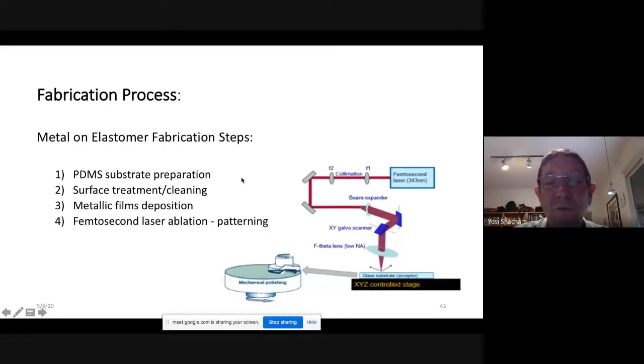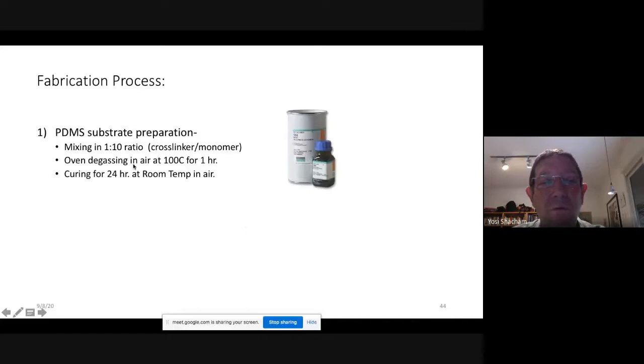First, one of the technologies which is very promising now, and many people are doing it, and we bought this system a few years ago. We are taking a laser, a femtosecond laser. We're using the 343 nanometer wavelength, which is ultraviolet. We're using pulses of approximately 270 femtoseconds. We have a Galvo scanner, so we can scan with the beam. First we prepare the substrate, then we do surface treatment and cleaning, then we put the metal, and then the laser beam is ablating the metal.